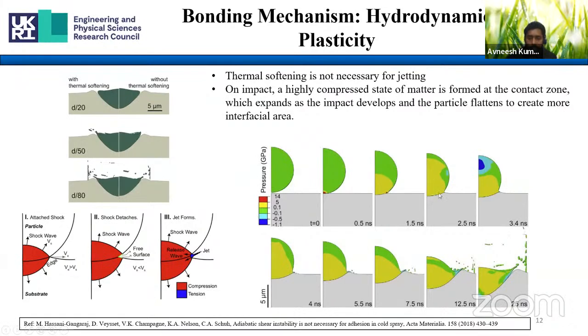The velocity at which this particle flattens, they named the contact edge velocity, and the velocity of the shock wave they named Vs, the shock wave velocity. Initially the contact edge velocity is very high, and slowly it decreases with time. There is a point where the contact edge velocity becomes lesser than the shock wave velocity. When that happens, these pressure waves start releasing from the edge of the particle towards the free surface. Further, this release of the pressure wave causes the formation of jets. You can see the same after 2.5 nanoseconds, the jet formation is there.